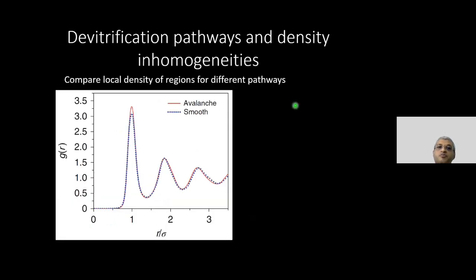Now, you can do a very simple analysis. We know where the crystallites grew, which means that we can look at the very initial time series of our images, when there are no crystals at all in the field of view. And what we can do is plot the pair correlation function. This is for an avalanche process, the red one here, and that's for a smooth growth process. So I'm looking at regions before crystallization happened, and I'm calculating how they are locally arranged.